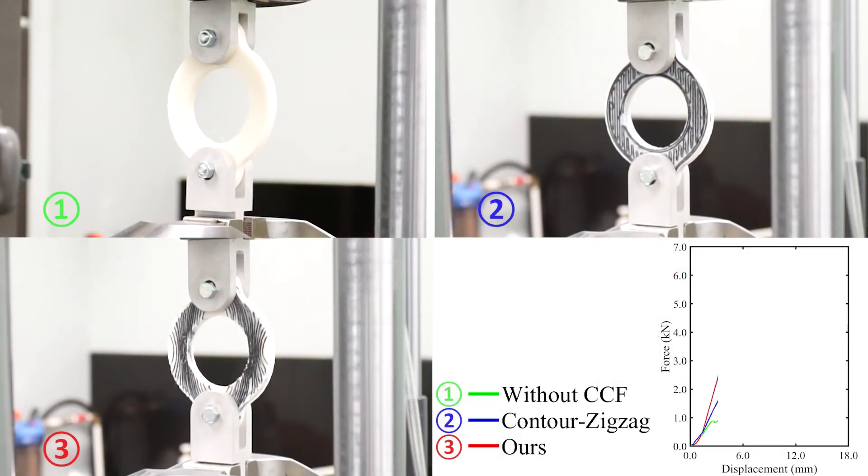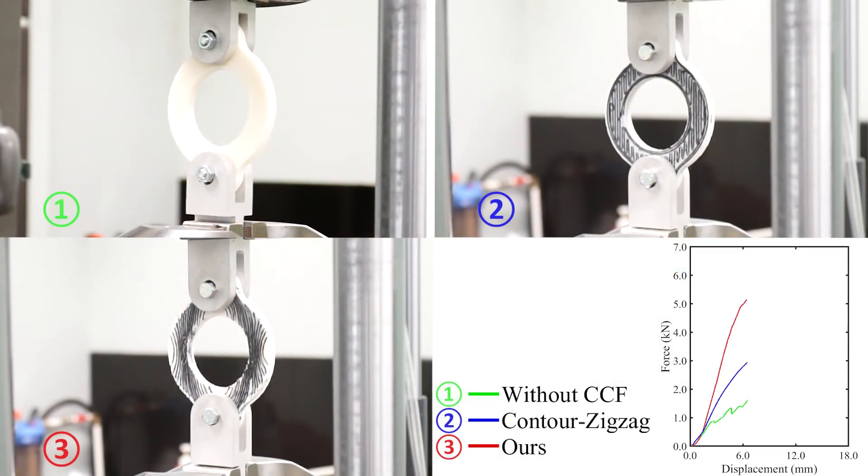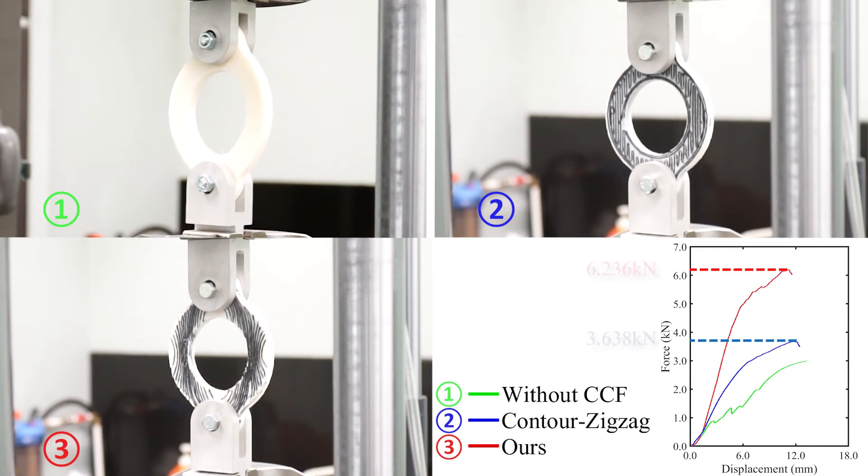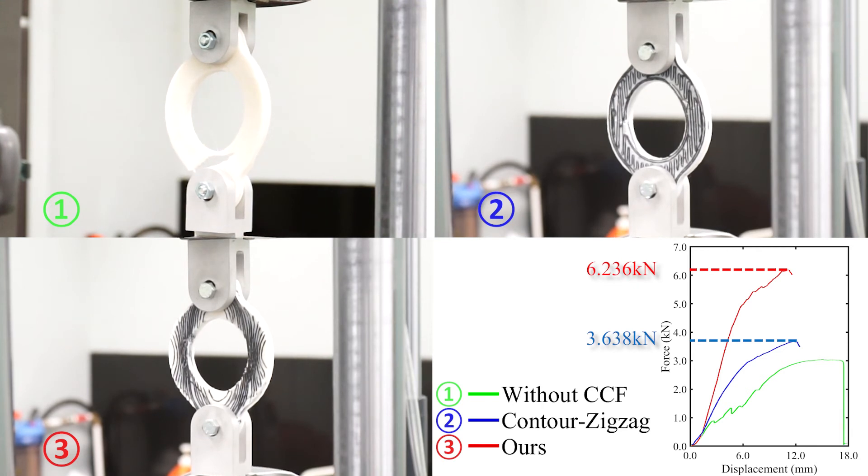Comparing to the toolpaths generated by commercial software, the breaking force is increased by 71% on this loop model by using our method.